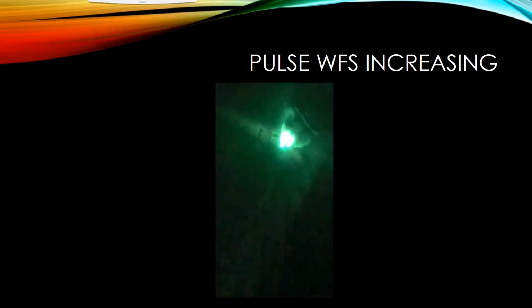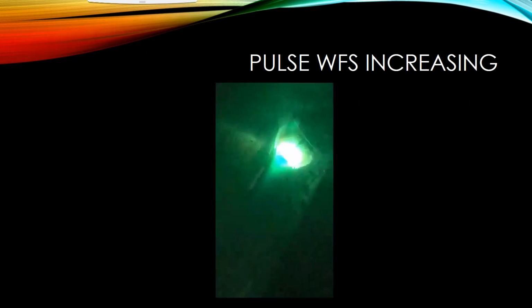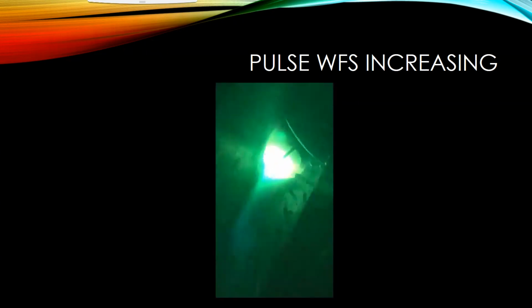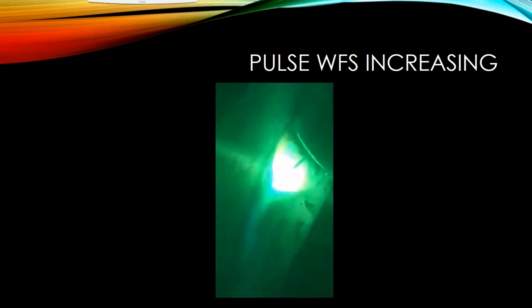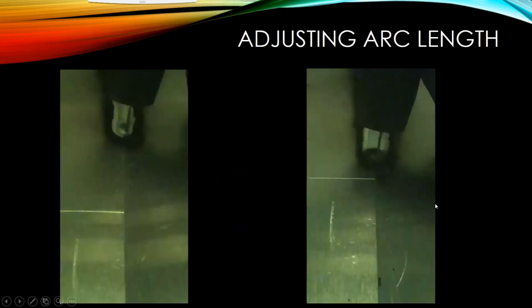So it maintains the arc, but as I'm increasing that wire feed speed, that puddle is getting more fluid, it's getting hotter. You can start to see now we're starting to penetrate more into the plate. So that's one adjustment. Synergically, it's going to adjust. Now let's look at our other adjustment for pulse. Let's look at adjusting our arc length.